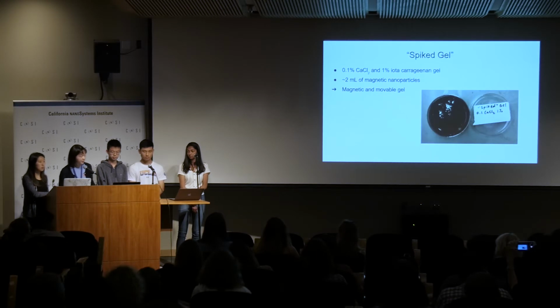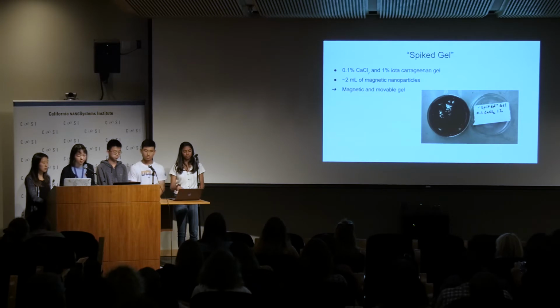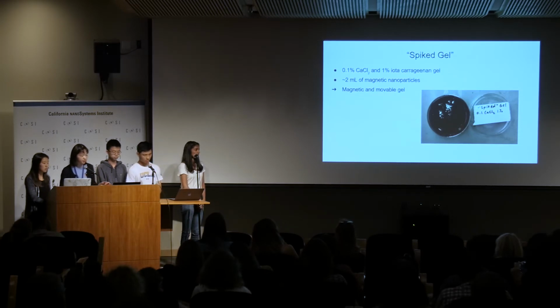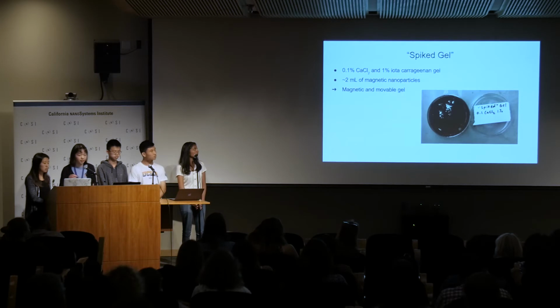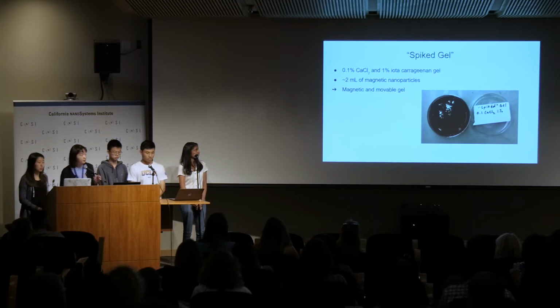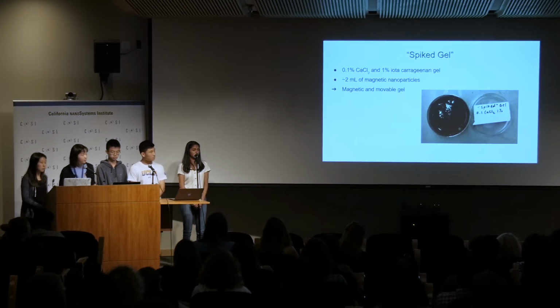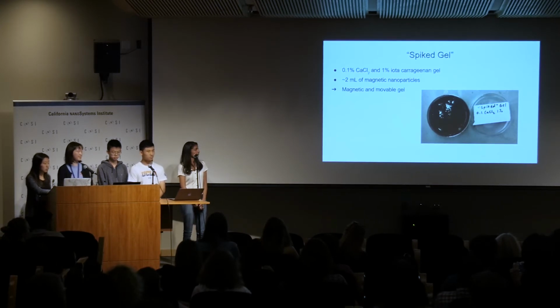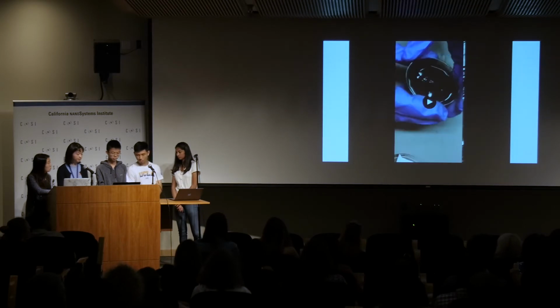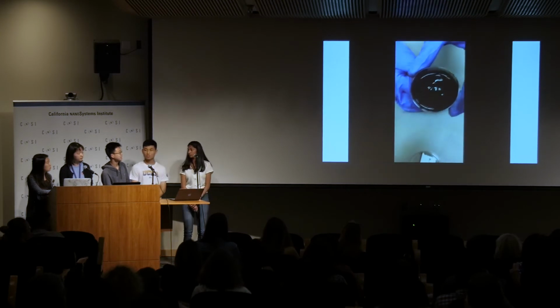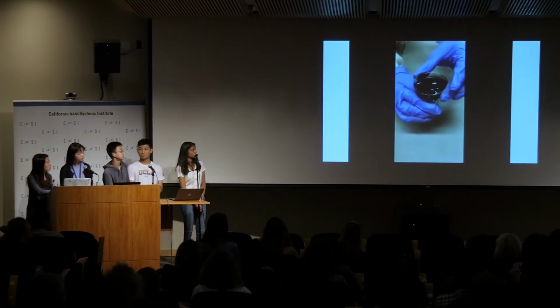So at this point, we haven't really got a magnetic gel, so we decided that we would just take one gel that was not too stiff but not too liquidy, and we would just spike it with a whole bunch of ferrofluids. So in our 0.1% CaCl2 and 1% iota-carrageenan gel, we added around 2 milliliters of magnetic nanoparticles, and that made the gel extremely magnetic and movable. As you see, it responds to magnetic fields, like we hoped.